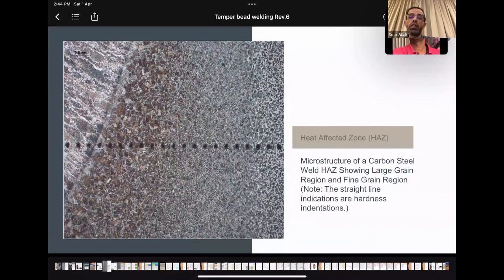This is another photo for the coarsened grain area. It is clear. And this photo is for carbon steel welded using high heat input. So this is the reason why the grain gets coarsened or enlarged near the weld toe. And this dashed line is for hardness indentation.